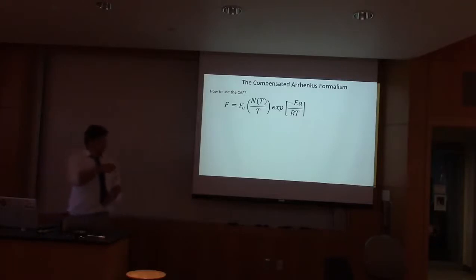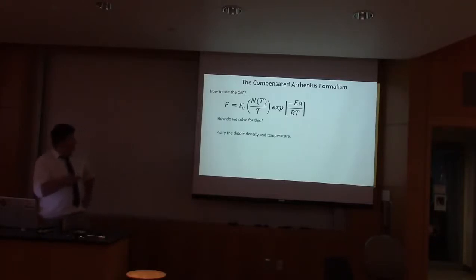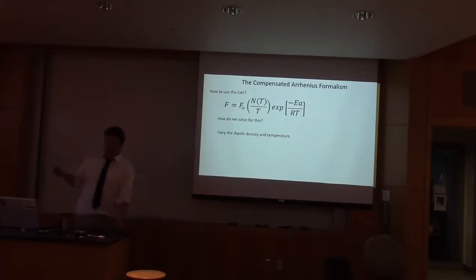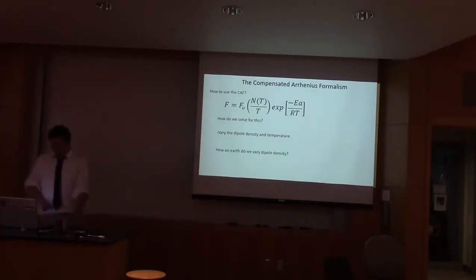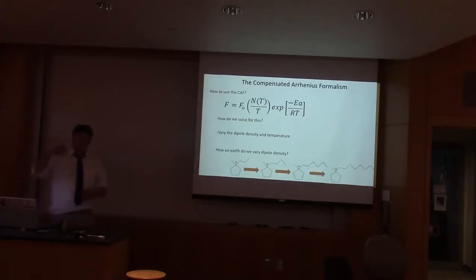We now know how we use the CAF. We've got a couple of variables to deal with: the dipole density and the activation energy. In order to solve for this, we need to vary the dipole density and vary the temperature. It's very easy to vary temperature. We do a 5 to 85 degrees Celsius range. But in order to vary dipole density, we use these 4 different cations with varying alkyl chain length. The idea is that as we add members onto the alkyl chain, the molecules in the liquid have to be further apart from each other, thus varying the amount of dipoles per unit volume.